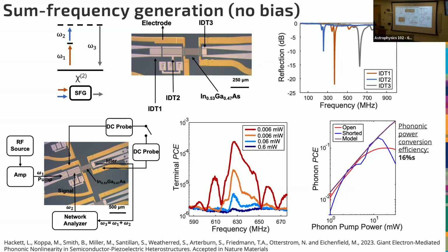We're constrained in the lithium niobate thin film thickness we can pick, which completely determines the dispersion of the waves. Like I said, growing the material is very challenging, and optimally picking that carrier concentration requires better precision than we can actually achieve. So going forward, we'd like to optimize this. And we think it should be possible to get to essentially unity conversion efficiency. But 16% is pretty good for a first pass.